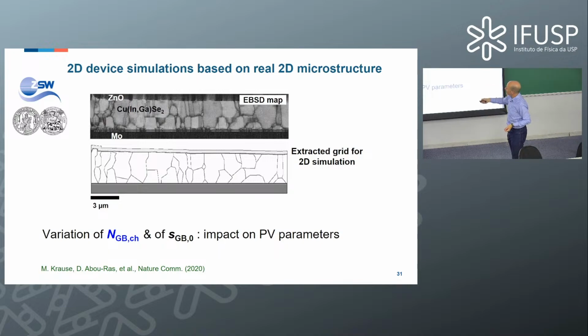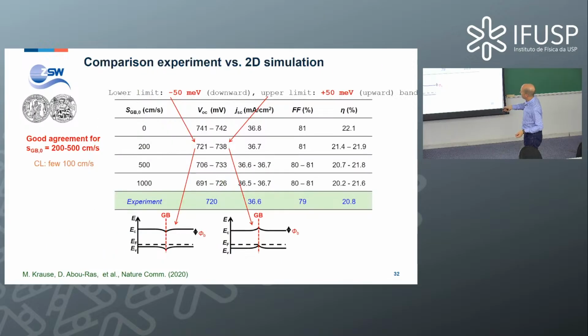And then what you can do is to vary exactly the excess charge density and the prefactor, yes, that we have from our evaluation of the CL measurements, in order to see, okay, how do these parameters affect the device performance. And we did that back in 2020. But here what we did was to use just two values for the downward and for the upward band bending, right? So just two extreme values. And then we varied the prefactor. So the prefactor was varied between 0 and 1000. And these are the experimental values for the open circuit voltage, for the current, short circuit current density, fill factor, and the efficiency of the solar cell.